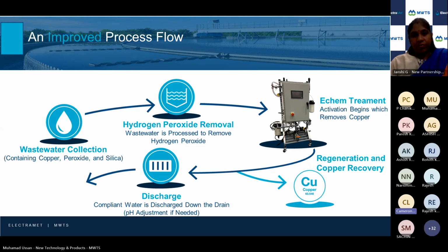And now the net waste product of our process is a high purity, 99.99% pure copper metal. So you can now recover this as a new revenue stream, which helps reduce the total cost of ownership of this process, but also helps you meet ESG goals by not sending any waste to landfill. And more importantly, for every pound of copper that's recovered, that correlates to about 4 to 6 pounds of CO2 that is not emitted because you no longer have to mine that little bit of metal from the virgin ores.